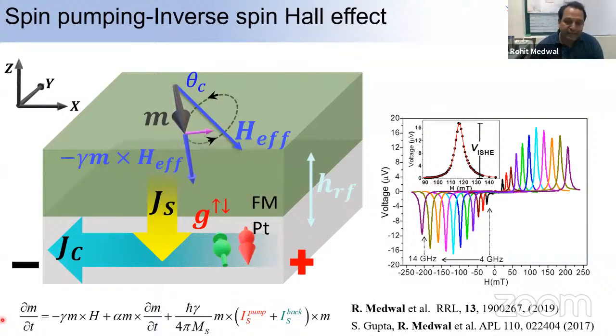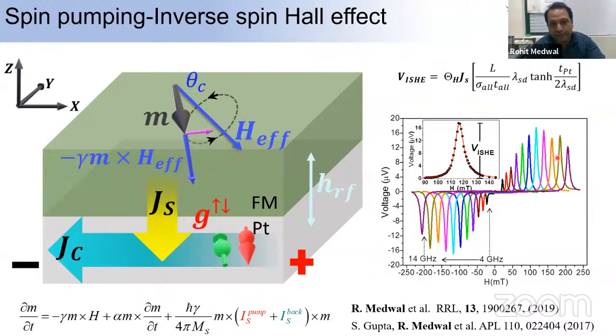We can clearly see that when you have a positive magnetic field, the polarity of the spin Hall voltage is high, positive. When you reverse the direction of the magnetic field, the voltage signal reverses. So this clearly shows that the spin motive force is responsible for this spin Hall voltage. We have clearly shown that we can generate the spin voltage by the precessing magnetization and detect it using the inverse spin Hall effect technique.